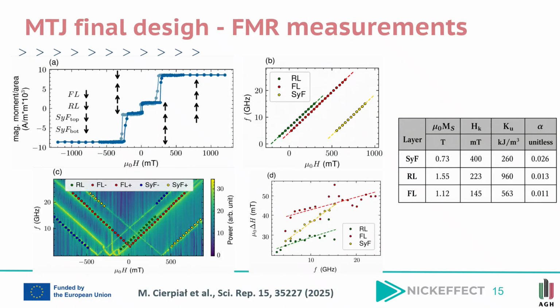Ferromagnetic resonance measurements, FMR, were performed to investigate the dynamic magnetic properties of the final optimized MTJ stack. The measurements enabled identification of the resonance modes associated with the synthetic ferrimagnet, reference layer, and free layer, as well as extraction of key magnetic parameters relevant for STT-MRAM operation. Panel A presents the hysteresis loop of the complete MTJ stack, showing the sequential switching behavior of the free layer, reference layer, and synthetic ferrimagnet.